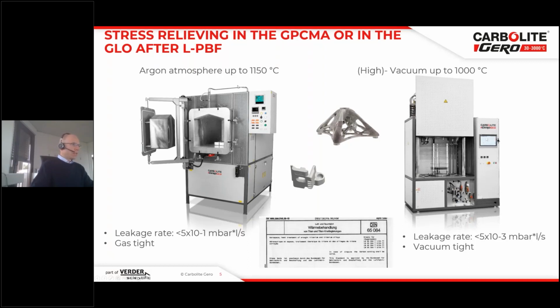The first solution is an industrial product which is used all over the world. It's for stress relief heat treatment up to a temperature of 1150 degrees C under a very high purity argon atmosphere. Of course, we measure the final oxygen content to really make a quality control of the process. So we have the oxygen value monitored and under control. This is our furnace. It's the GPCMA, a general purpose chamber furnace with modified atmosphere for high quality heat treatment of printed parts by a laser or by an electron beam. That's our first solution.